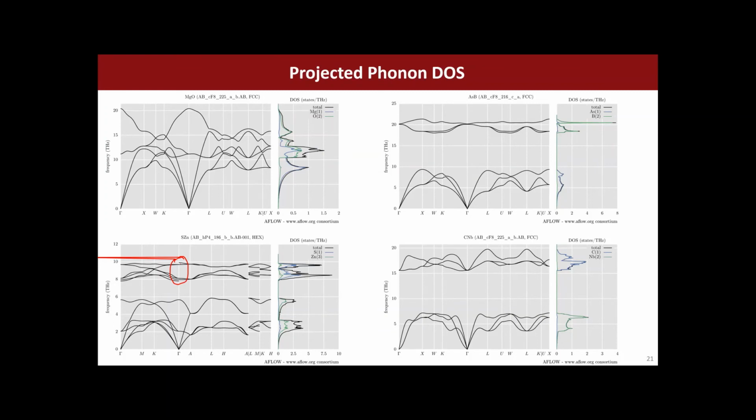Can we also cure this by brute force by increasing the supercell size? No, because the harmonic approximation does not include that. You would need to use some other techniques, but not the finite displacement method. That term is just not in the harmonic approximation of finite displacements.